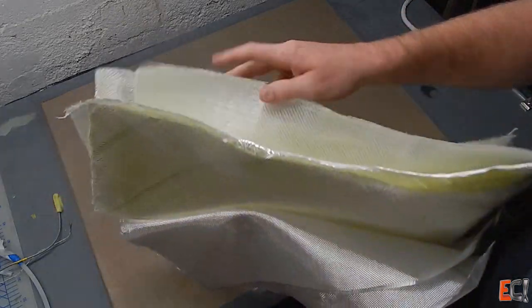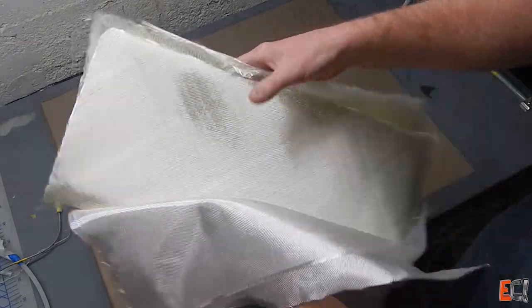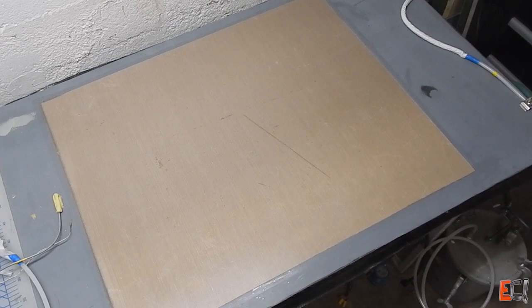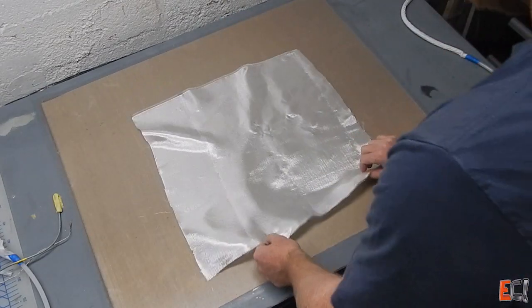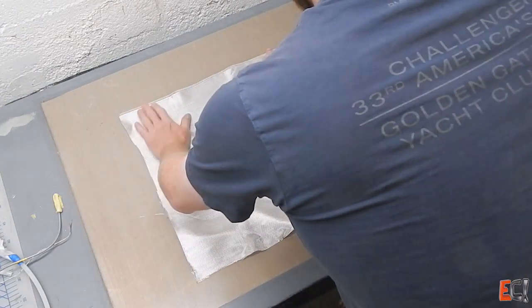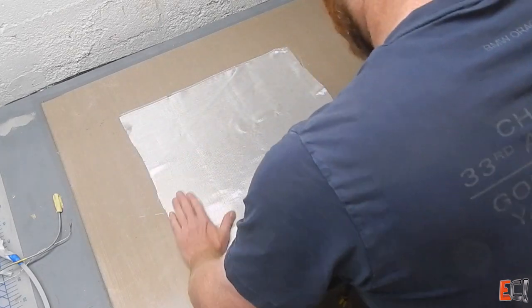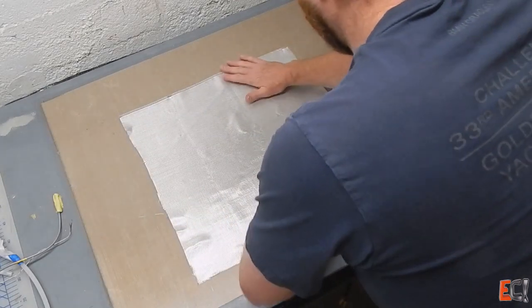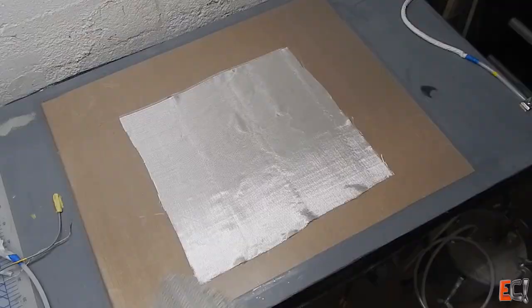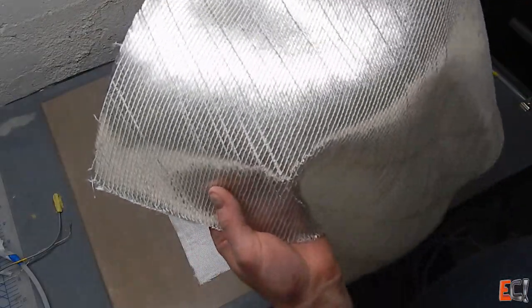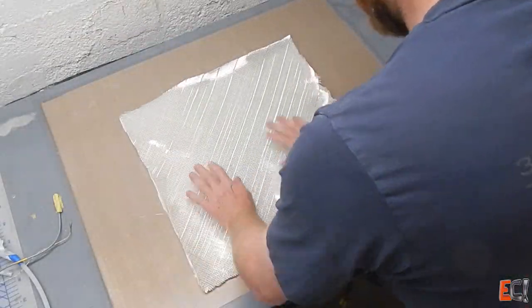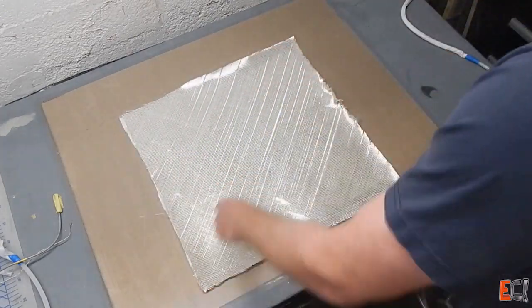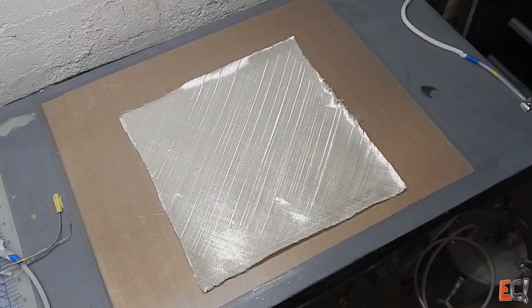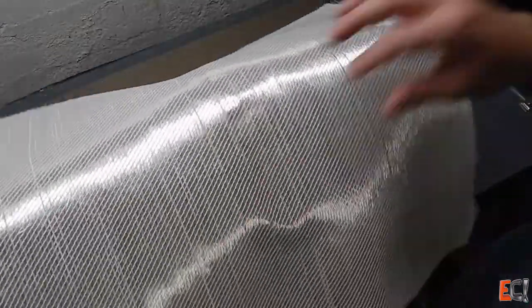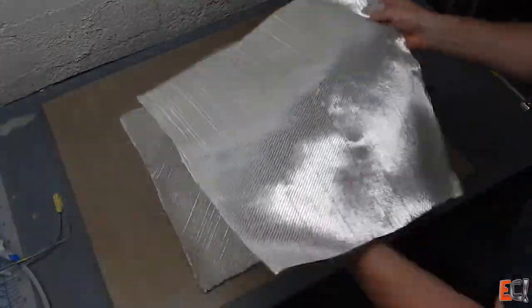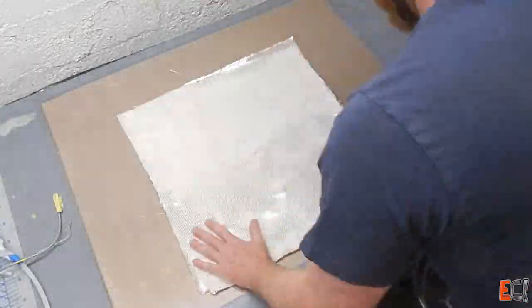It has surface plies of 200 gram woven e-glass, or 6 ounce, and 12 ounce, 400 gram-ish, three plies in the middle of stitched biaxial. This material here, you can see this ply, the fiber is running at plus and minus 45 to the edge of the panel, and this middle piece has been cut, so the fiber is running at 0 and 90 degrees to the edge of the panel.